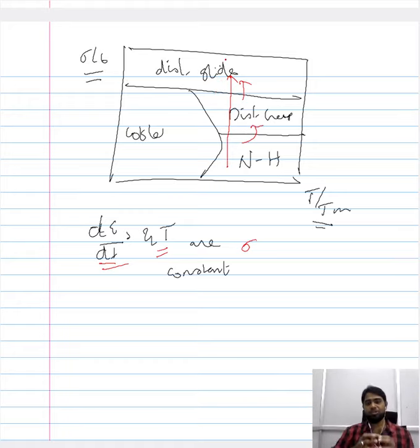So this particular deformation map can also be used to trace, for a given constant creep rate, what the different mechanisms are that occur one after the other in a series. How the creep mechanism shifts from one to another can be viewed from this Ashby's deformation map. Essentially what Ashby's deformation map tells us is which mechanism is operational at a given point. For a combination of a given stress and temperature, which creep mechanism is operational can be gained from this deformation map.